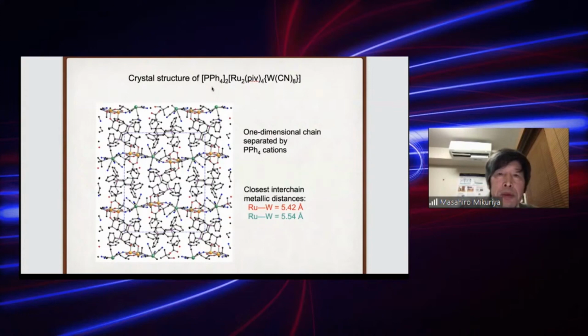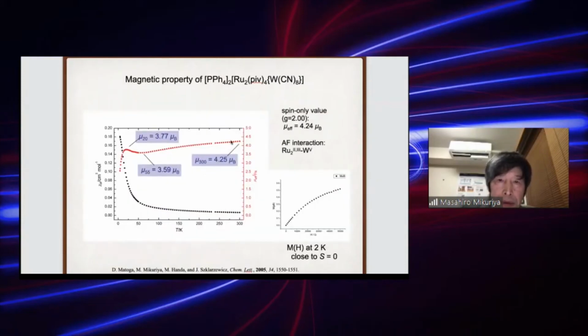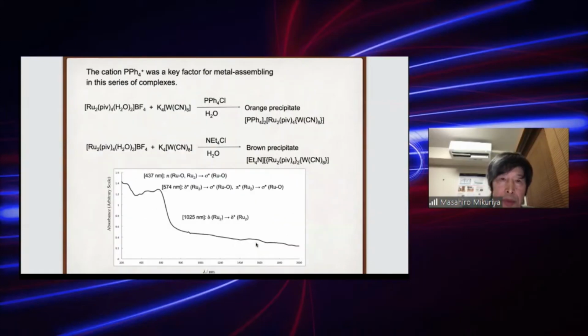And when we put tetraphenylphosphonium ion to this system, we could obtain similar compound, but in this case, we can see the chain structure and this counter cation. This one shows a similar, a kind of paramagnetic behavior, but this one was antiferromagnetic ones. So tetraphenylphosphonium ion is some key factor for metal assembly.